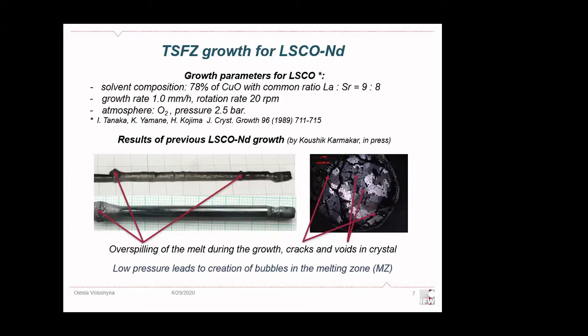And as you can see, the crystals have a lot of voids and cracks on the cross section. And from the shape of the crystal, we can say that during the growth, we have a lot of overspilling of the melt. And my first experiment was carried out with the same growth parameters. As it turned out, the low pressure of oxygen leads to the creation of bubbles in the melting zone. And when we have such a bubble in the melting zone, it influences the shape, as you can see from these videos. Usually the presence of a bubble leads to overspilling, obviously, and to tilted growth of the crystal due to the off-axis rotation of the feed rod and the seed with the growing crystal.